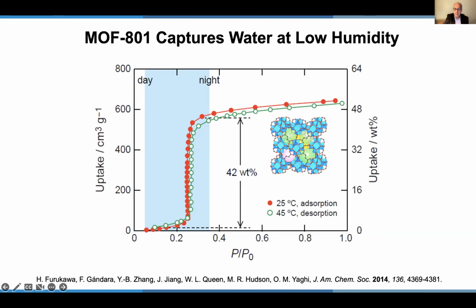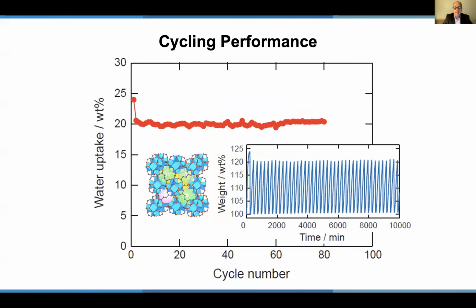And you can take that water in and then take it out at 45 degrees C, which gave me the idea that perhaps we can use such a material in the desert where, let's say at night, you take up the water from air when it's humid and cool, and during the day, by exposure to sunlight, you can release the water. So that was our idea. And we just wanted to make sure that the water can go in and out easily. And this plot shows that this material can take in water and the water can be removed over, we show here, about 80 cycles.